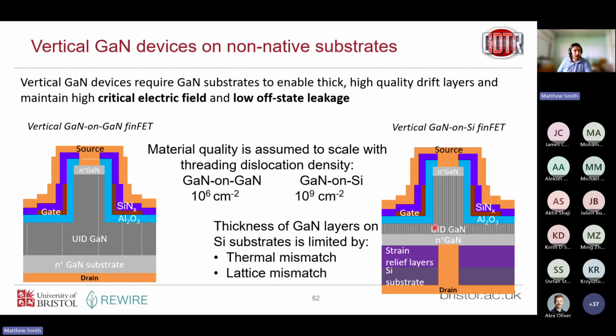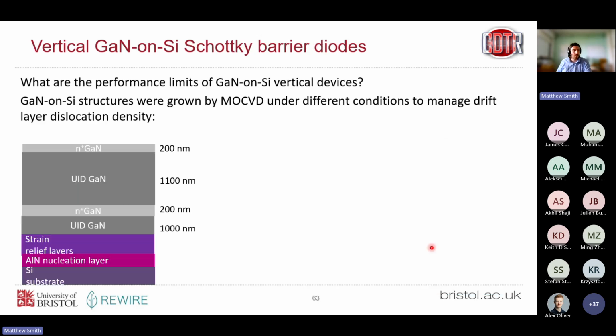An additional complication here for GaN on silicon is the thickness that we can grow. When we grow GaN on a GaN substrate and cool it back down to room temperature, everything's expanding and contracting at the same rate, because GaN has the same thermal expansion as the GaN substrate. That's not the case for GaN on silicon. So that's part of the job of all these strain relief layers, to manage that. But ultimately it means that we're limited in how thick we can grow gallium nitride on these non-native substrates. So we gave it a go.